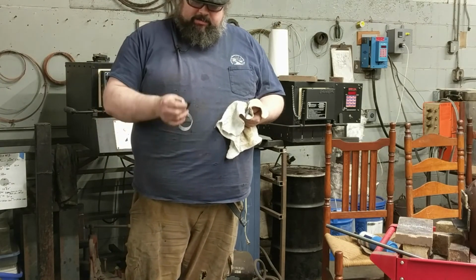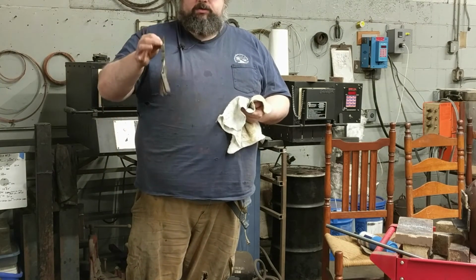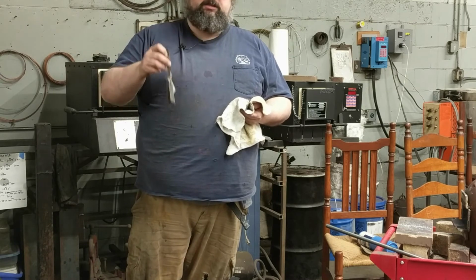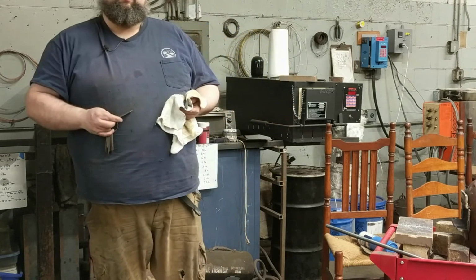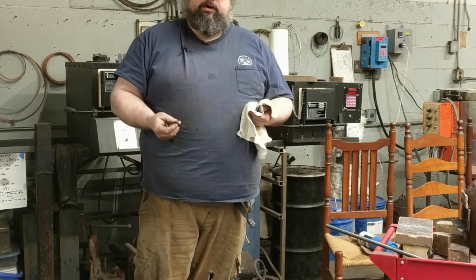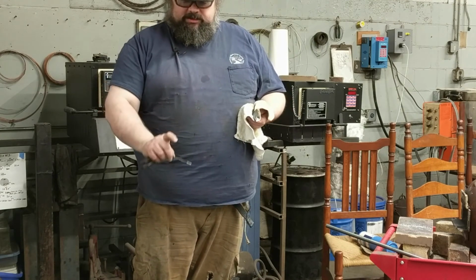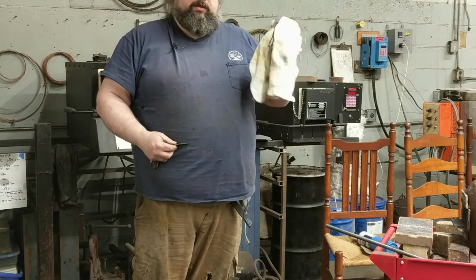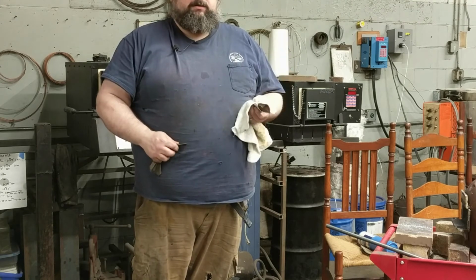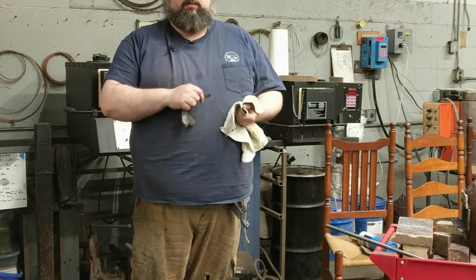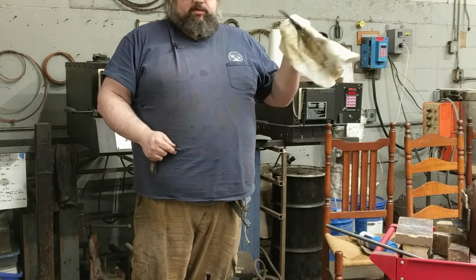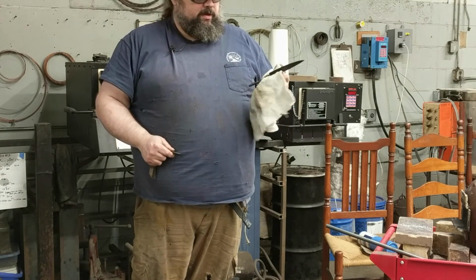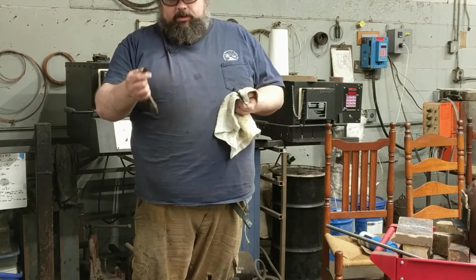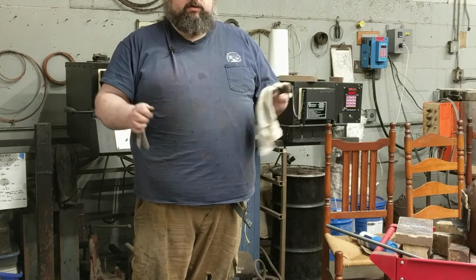I like to use these. I manufacture these. These are Rockwell test chisels. Each of these is set to a specific Rockwell hardness, and it's within a half a point or so across the whole piece. This is 64, and I know that 1084, if it's fully hardened, gets 64, 65 Rockwell max. Same with the 15N20 and 1080. So if I get this close to 64, I know it's fully hardened.